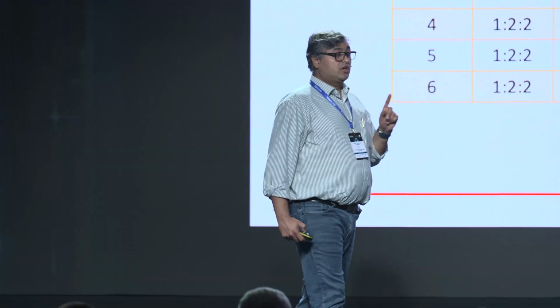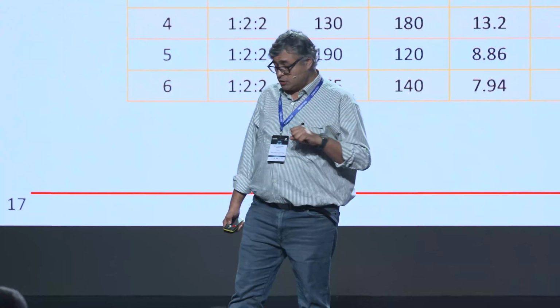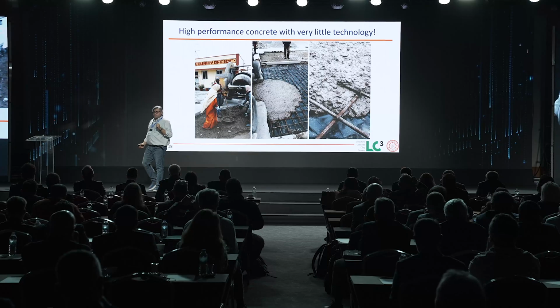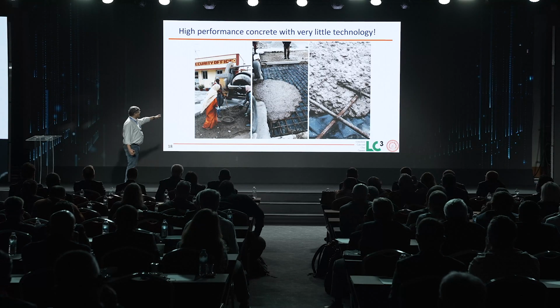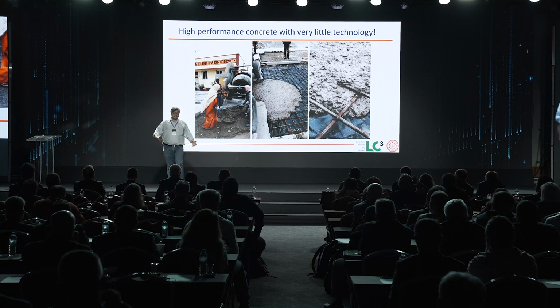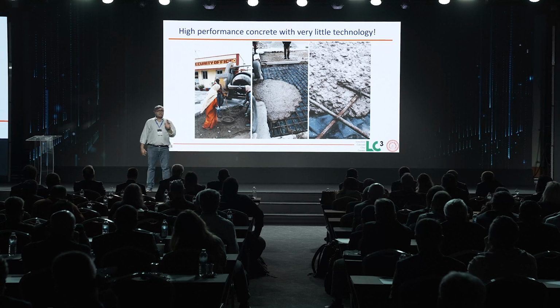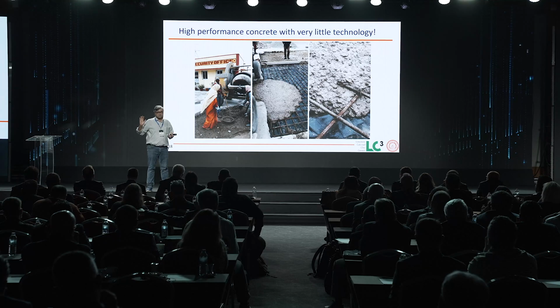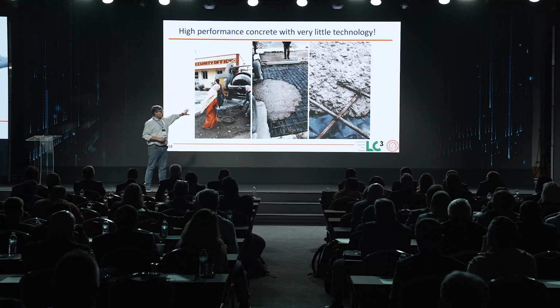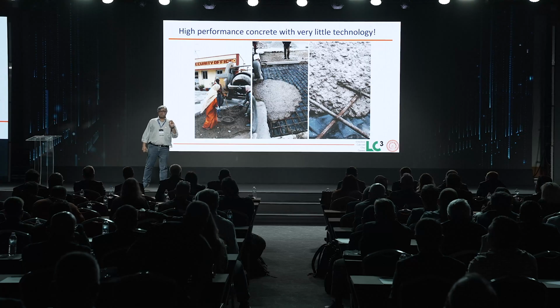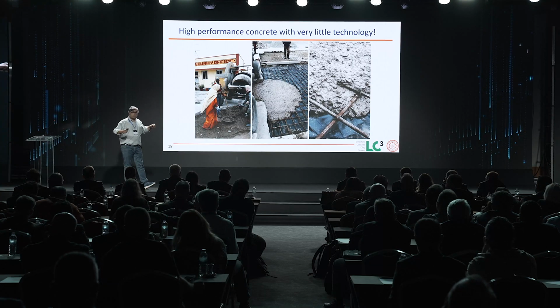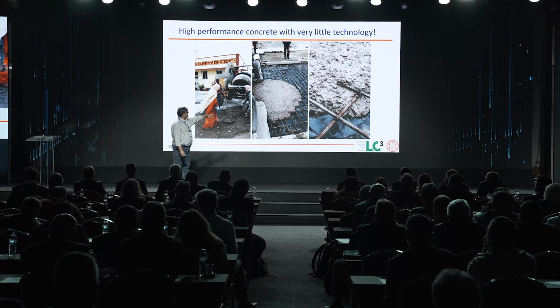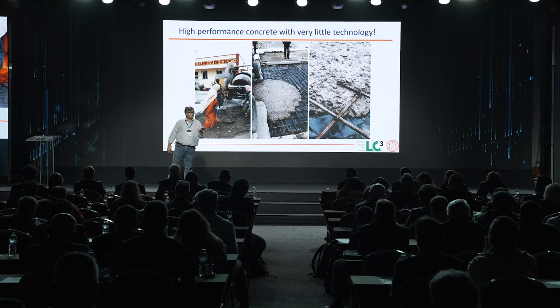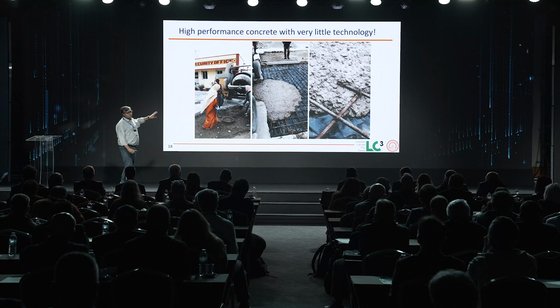We were less worried that if the concrete was used without any technology, you would be able to produce that concrete. We wanted to see if you give these very highly trained engineers, once again, some more technology, and you see the very high-tech concrete mixer over there. We gave them some technology, and we said, can you make some concrete out of it? The only quality control that we did in this case was we had a bucket of water in which we put a hole on the side. You cannot put more water than that in the concrete. You control the water to cement ratio. Just by controlling that, we made this pavement, 40 batches of concrete using this mixer. The average strength of the concrete was 53 megapascals. Just made this way, volume batching. This was in 2017, and you can see the beautiful concrete that was prepared. Yes, clay has a higher water demand, but even without a lot of technology, you can make beautiful, high-strength concrete.